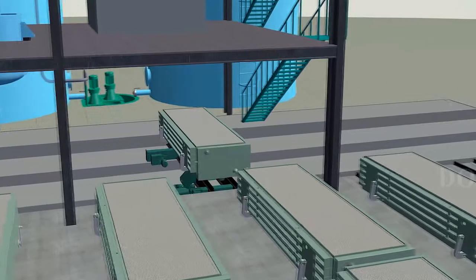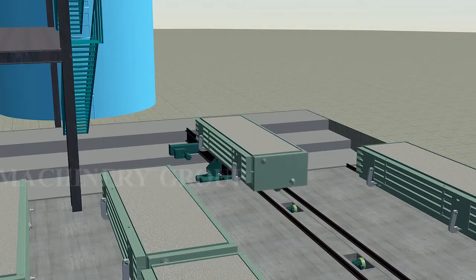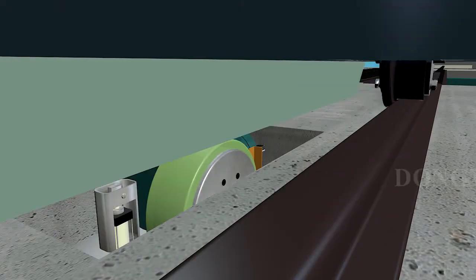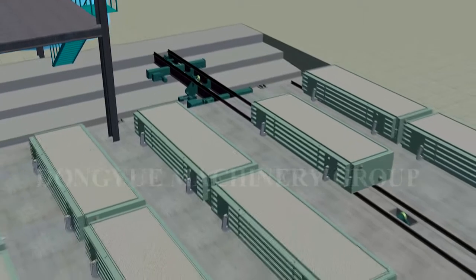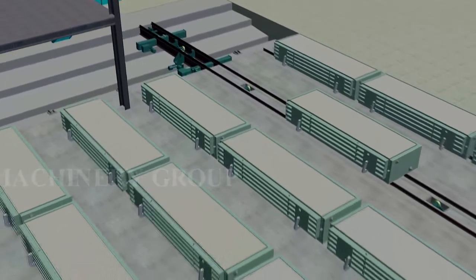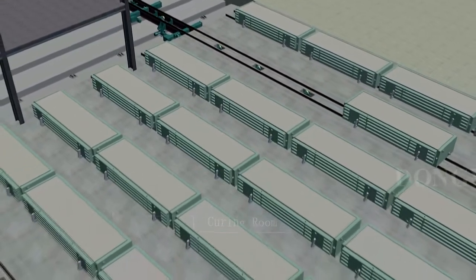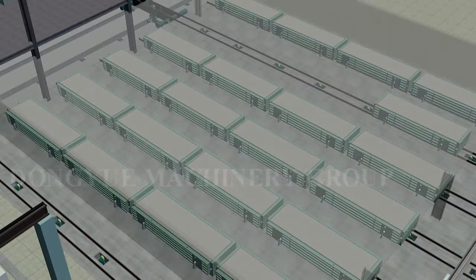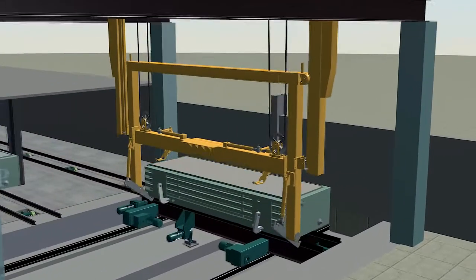After completing batching process, it comes into standstill for pre-curing process. Slurry in mold box will expand because of the hydrogen produced by chemical reaction of lime, aluminum, and water. After foaming, thickening, and solidifying, it becomes block cake. Block cake completes the hardening process to achieve the cutting requirements at certain temperature. Mold box is transported to cutting area by reversal crane.